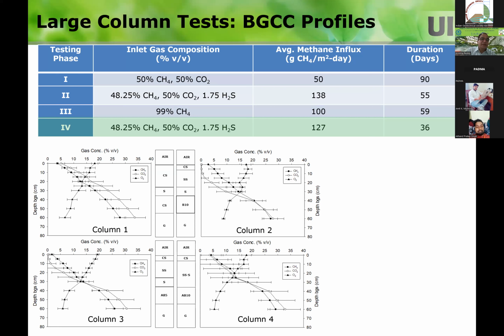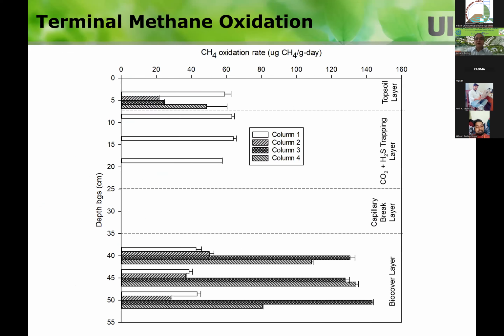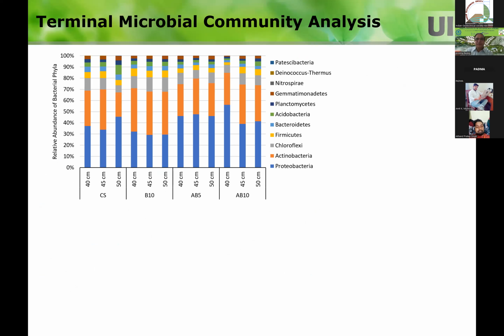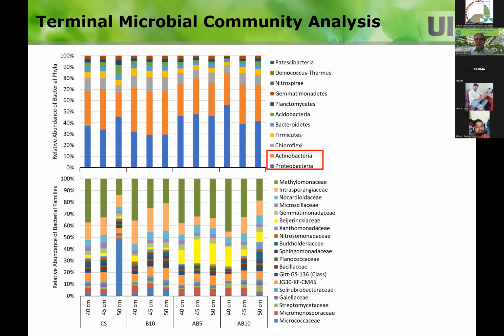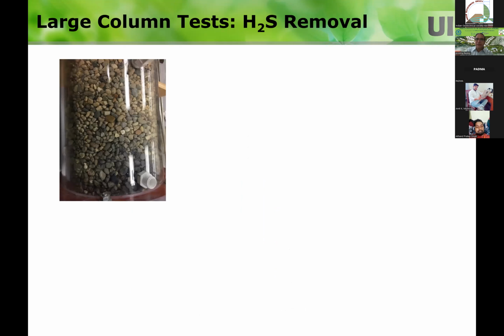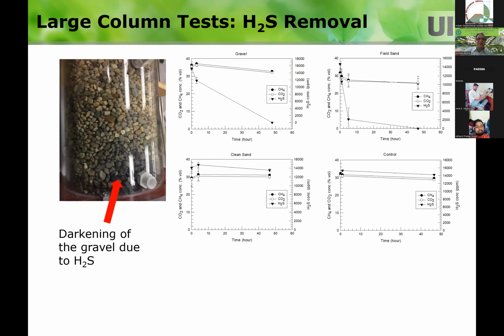So these columns again reveal that CO2 can be sequestered by slag, and methane is converted into CO2 by the biochar amended soil. I can show a lot of data on what we did in terms of the microbial characterization. We looked at whether we have type 1 methanotrophs or type 2 methanotrophs under certain conditions. The presence of type 2 methanotrophs led to higher methane oxidation. And then we looked at H2S removal, and we found out that H2S was not really transported into the biochar amended soil or into the slag.